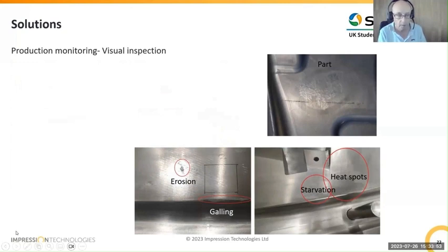On the dies themselves at the bottom, the one in the middle, erosion, can be caused by either a lack of lubricant, or sometimes the wrong kind of lubricant, where you can get a chemical erosion rather than physical erosion. So you get a chemical interaction between the die and the blank. Galling, which is just below there, quite often occurs on sharp radii, and has to be taken care of. And the one next to it, if we don't apply sufficient lubricant, then we can see scratching on the dies from the part moving across it, or we can also see heat spots developing because we're not using the lubricant correctly to cool the dies as well as the internal water-based cooling that goes on.